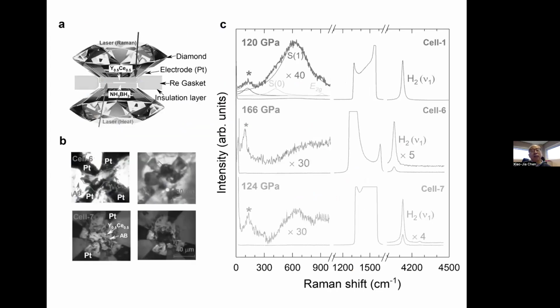Following their design for synthesized material, we also work in this field. Later, we choose NH3, BH3 as hydrogen sources. We are thinking to reduce the synthesis pressure because in the early measurements the pressure was pretty high, above 200 GPa or near 300 GPa. We're thinking whether we can lower the synthesis pressure